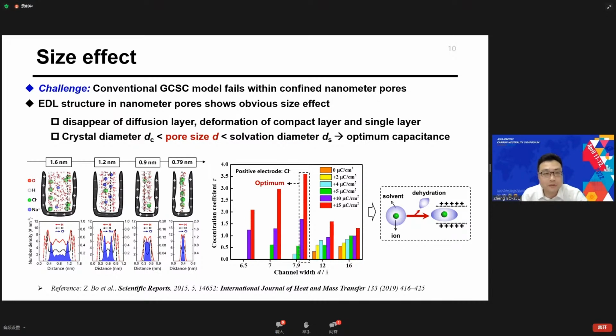Using molecular dynamic simulations, we found that the ion distribution structure in nanometer pores shows an obvious size effect: as the pore size decreases, the diffusion layer disappears, the compact layer deforms, and a single layer structure can be observed. The mechanism behind ion density and capacitance can be understood when the ion distribution takes this single layer structure.